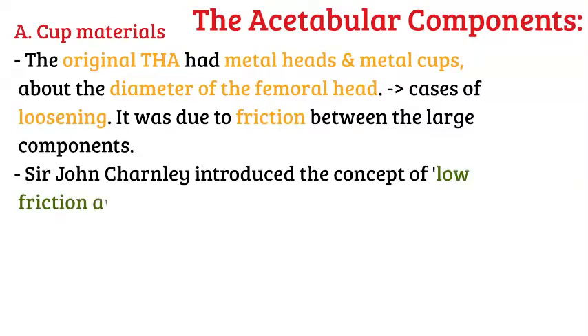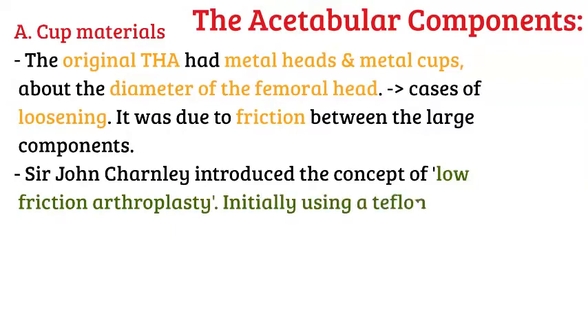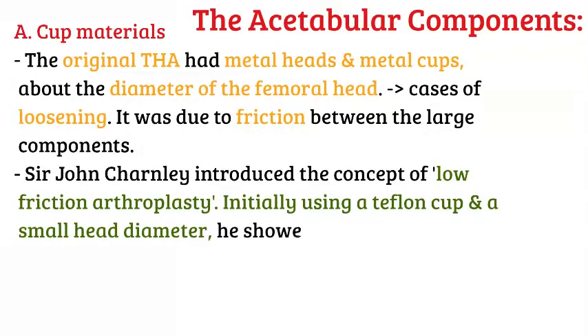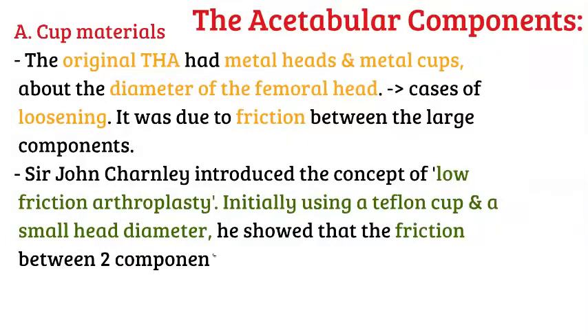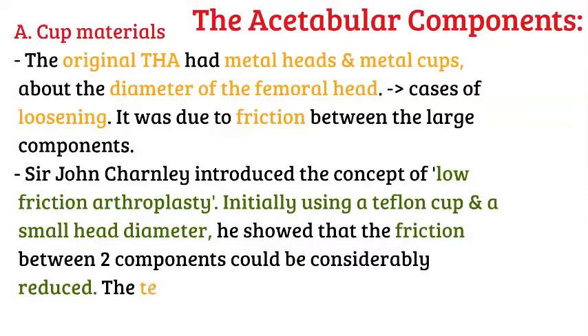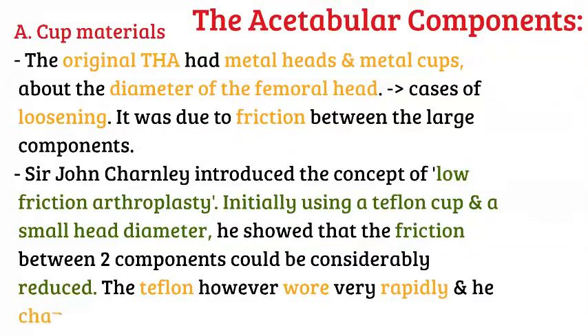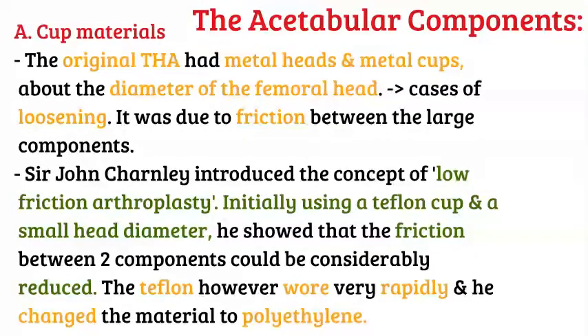While many of these did well, there were cases of loosening. It was attributed to friction between the large components. Sir John Charnley introduced the concept of low friction arthroplasty. Initially, using a Teflon cup and a small head diameter, he showed that the friction between the two components could be considerably reduced. The Teflon, however, wore very rapidly and he changed the material to polyethylene.